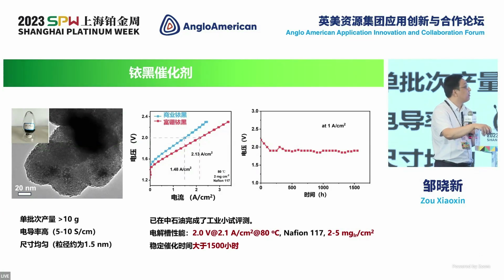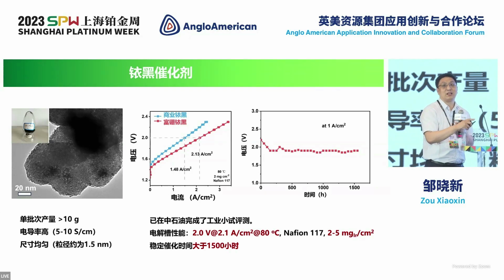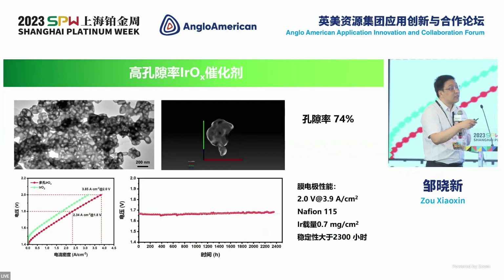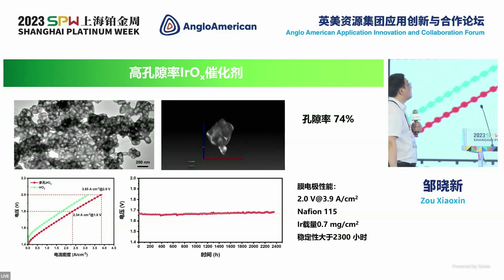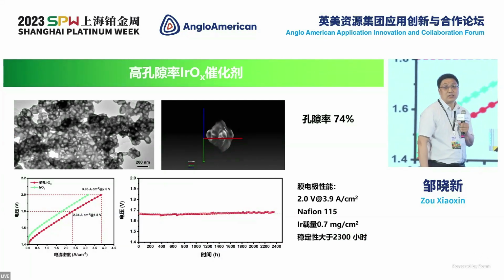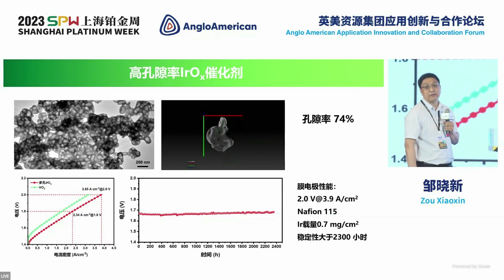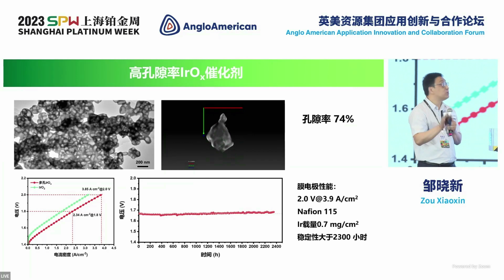And this year we are also working with China Petroleum on pilot testing and evaluation. In terms of activity, it is meeting the target, and it can perform stably for 1,500 hours. This year we're also going to use it in an electrolyzer stack. In the membrane electrode, the iridium loading is still very high. In order to reduce the iridium loading, very recently we developed a structure. It's very porous. The porosity can be over 74%.